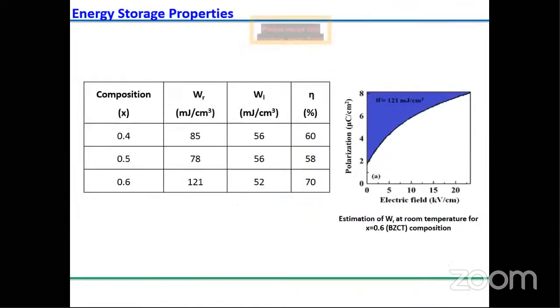Then we estimated the energy storage property by using that expression. So U recoverable, as we showed in the beginning, is the integral from Pr to Pmax of P dE. This is your electric field, this is your polarization. You integrate and you get those values. So we estimated the energy storage by using the dynamic method. We observed the recoverable energies and efficiencies, tabulated here. We got for 0.6 an efficiency of 70 and WR equal to 121 millijoules. So from these results we can conclude that this BZT at x is equal to 0.6 composition shows the better ferroelectric, better dielectric properties as well as energy storage properties.